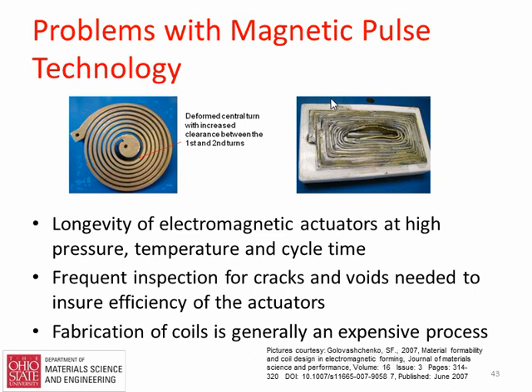So magnetic pulse welding obviously helps to bring down the collision process to a lab scale, and do things inside a lab or a closed industrial environment. But there are some problems with magnetic pulse technology, and these have been long-standing. The main one is it needs a coil which needs to survive through high pressures and high temperatures. If the cycle time for every single shot is really low, then the coil has to heat up. There's no way around the Joule heating, and the pressures are obviously very high for short times, and if there's any failure of the insulation material, then that's quite catastrophic for the coil, because once a spark can start going through the coil, then it can ruin the coil right away.